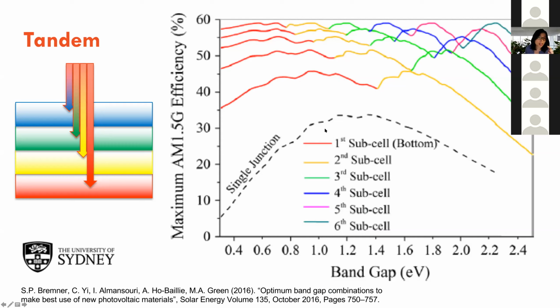But if you stack two materials together, and you have the top band gap of around 1.6 eV and then a bottom cell with a band gap of around 0.9, you can see the theoretical efficiency jumps by 10%. So you can see the advantage of stacking different materials together with different band gaps to make the most of the sunlight. And with this 3-junction tandem, you get more than 50%. And as you go up, with more stacks, the increase becomes marginal. So you have increased complexity, a lot of work, but not a lot of gain.